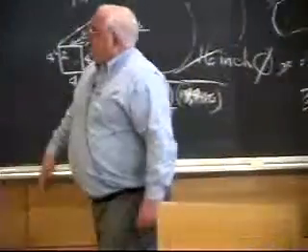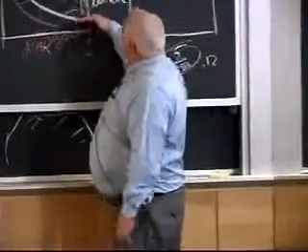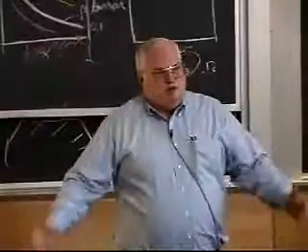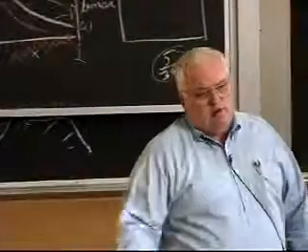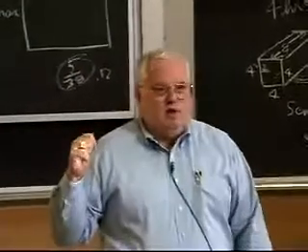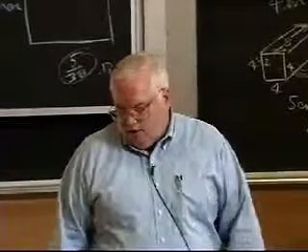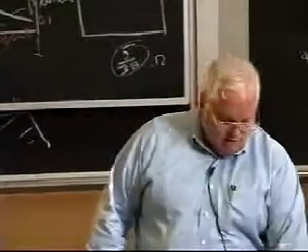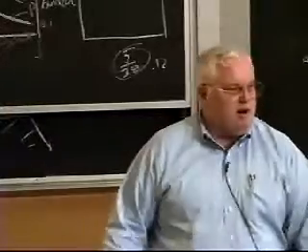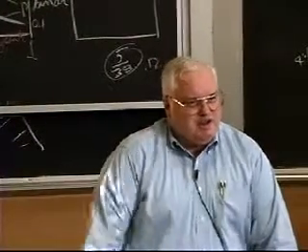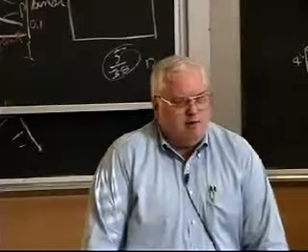Okay, well, in doing all this, maybe it's not 200 degrees, maybe it only got to 400 degrees. But given the fact that if I don't get up to 1200 degrees, I still haven't done the job. In fact, what I've done is temper embrittlement. And that's exactly what happens to these things. I hadn't prepared that. But you actually can do those things in your head. Sometimes I scratch them out on a piece of paper when people aren't looking.